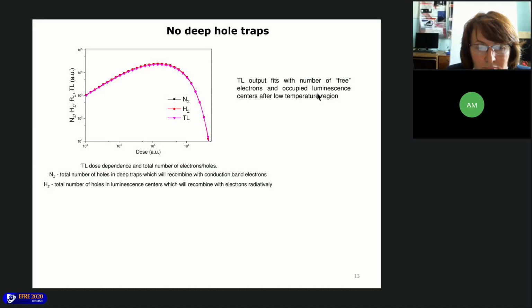In the figure, you can see that the thermoluminescence curve, the number of free electrons and the number of occupied luminescence centers after the low temperature region fit with each other. It can be seen from the previous consideration that competition between thermal stimulation transition PNE from the excited state to the conduction band and localized recombination transition D during heating causes non-monotony of TL dose response.